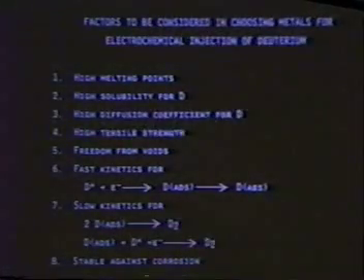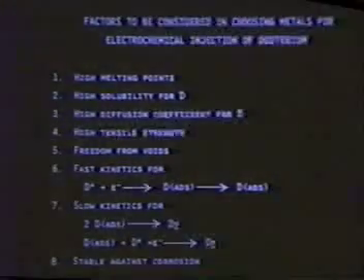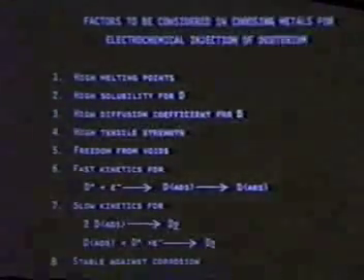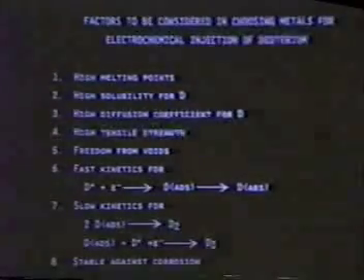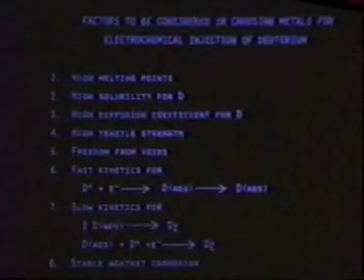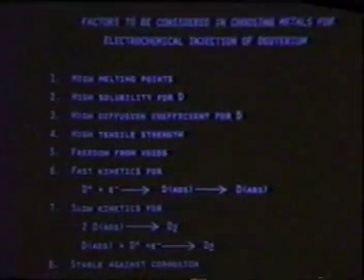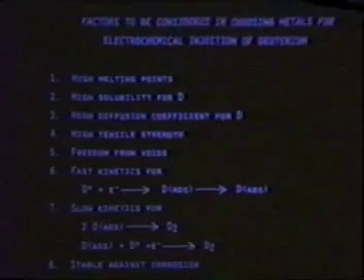There are strong indications in the work, for example, of Horkins and others, that hydrogen, when you take it out of the lattice rapidly, produces stress cracking. And thereafter, the hydrogen diffuses very readily through cracks and voids. That doesn't sound too good for this application. Then you want fast kinetics for this reaction and slow kinetics for the others. That requires a tailoring of the catalyst or the catalytic surface of the palladium to inhibit the reaction that you're not after. And then finally, you need stability against corrosion.